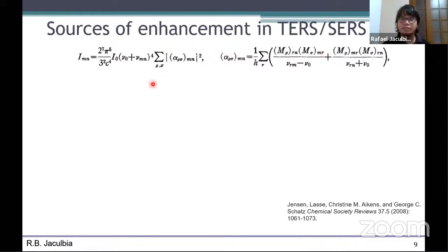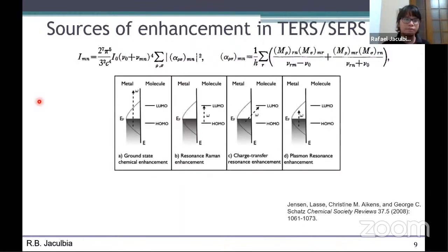And actually, TERS is mainly resonance with the excitation. Of course, there is the so-called ground state chemical enhancement, wherein just by placing the molecule in the metal environment, the Raman signal is slightly increased. But mainly, if you choose the proper wavelength of light, you can have a resonance enhancement by the intrinsic molecular states. So you excite the molecule from its HOMO to LUMO. Then you have the molecular resonance Raman.